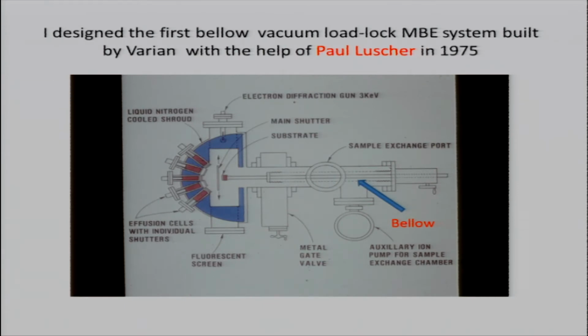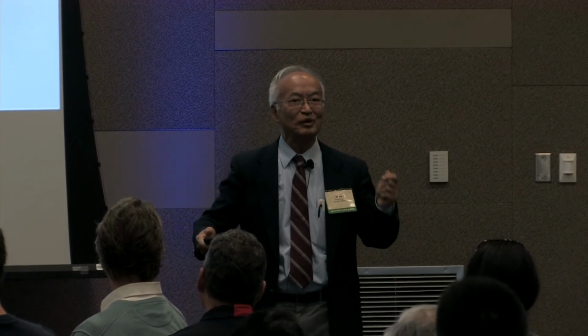Now, Hayashi was constantly monitoring my layers' luminescence, photoluminescence measurements, and he found that some days were good, some days not good. He said, what did you do? And I said, I didn't do anything, I grew the same way. But then I finally looked at all my data. I analyzed it, and, hey, during summertime, the luminescence of my aluminum gallium arsenide is horrible. During wintertime, it's pretty good. Why? Because in New Jersey, summertime humidity is very high. Whenever I open the system to change my substrate, the whole chamber has water vapor condensed in there. And I couldn't grow reactive aluminum gallium arsenide. So I therefore said, from the earlier days of load locks in the ion propulsion work, I'm going to put a load lock in there.